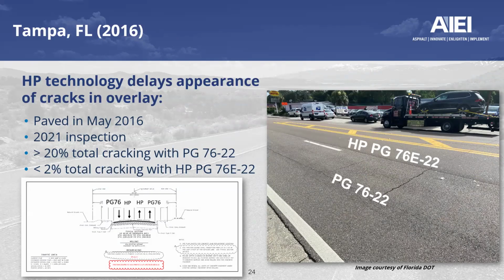Going down southeast to Tampa, Florida in 2016, the HP technology delays the appearance of cracks in an overlay. It was paved in May 2016. After a 2021 inspection, it was shown that there is over 20% total cracking with the conventional PMA in that lane, versus less than 2% total cracking in the lane that employed high polymer modified mixtures.